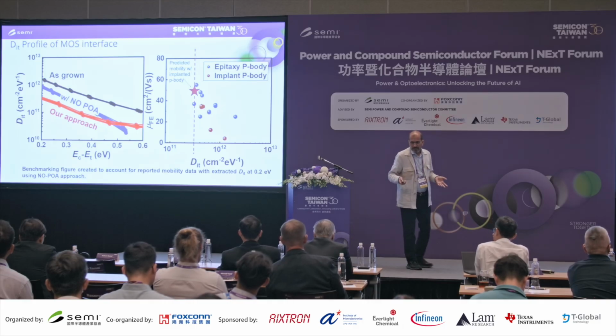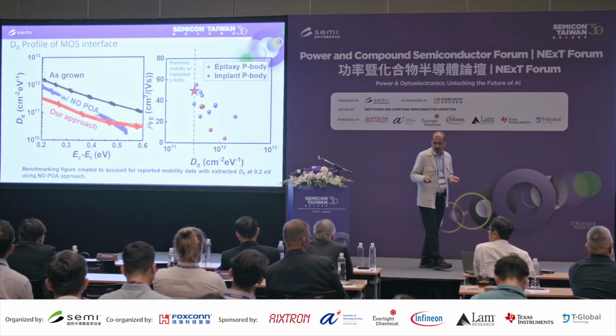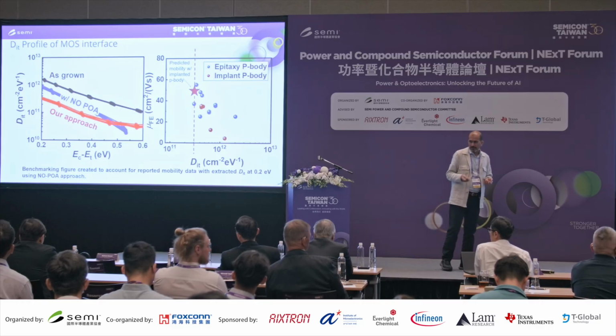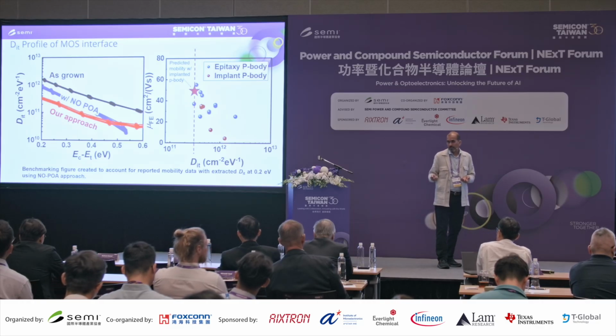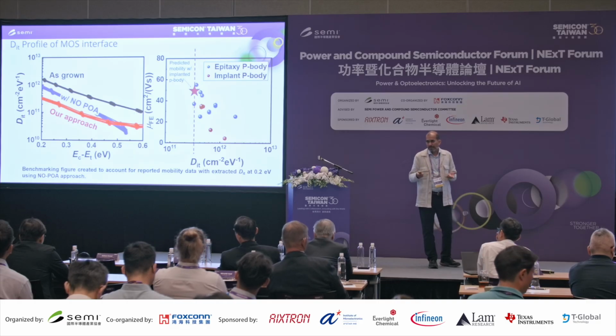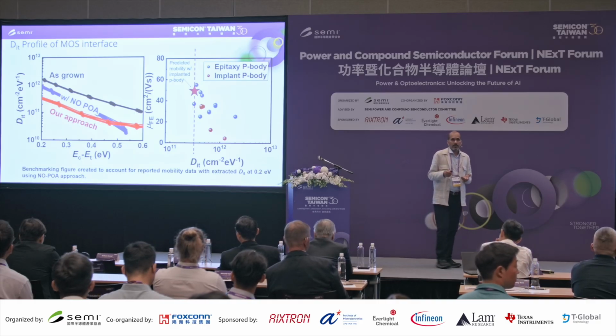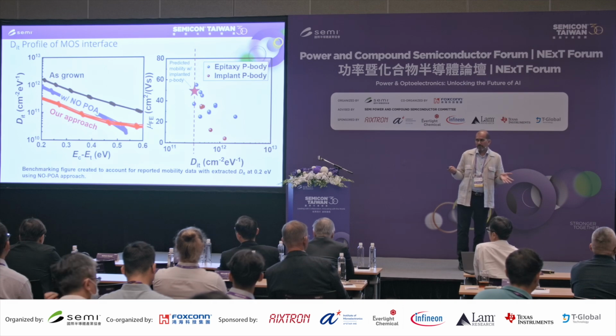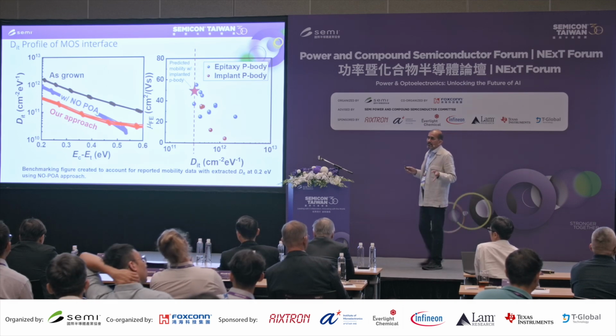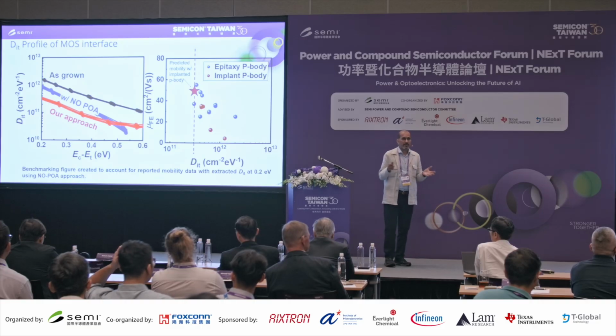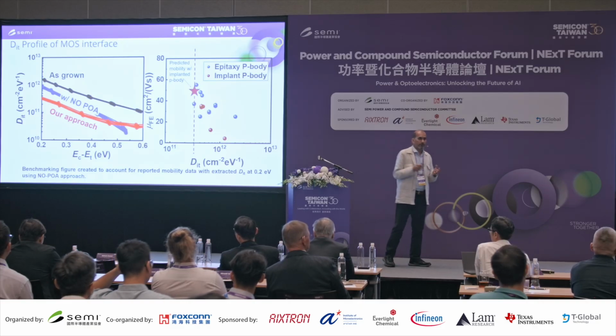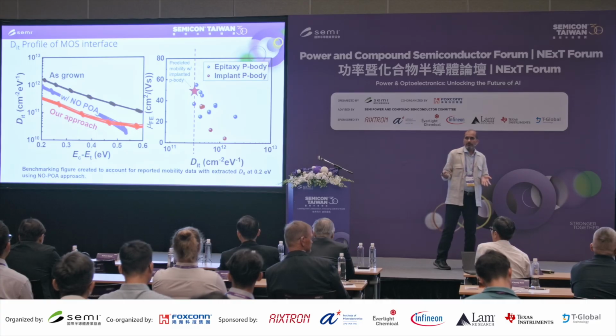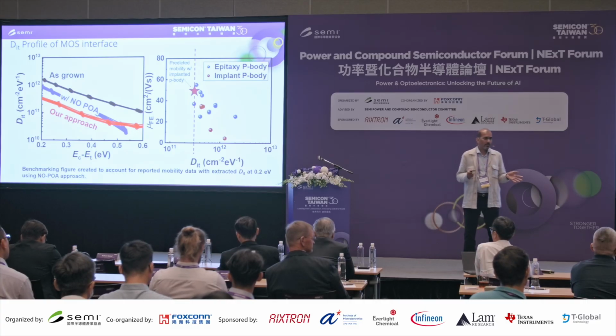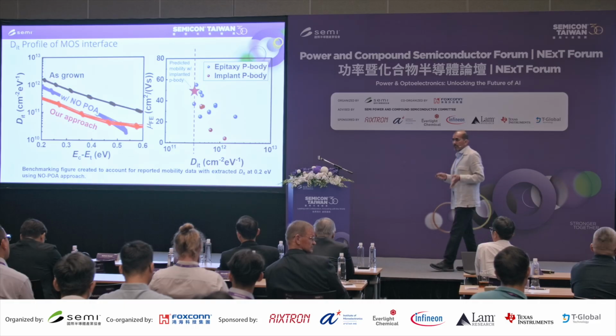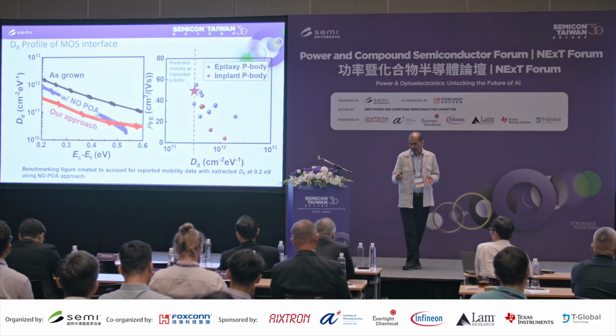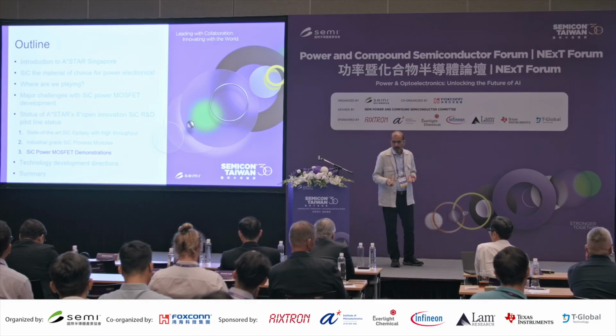This is just the DIT extraction, and you can see on the left side we have gotten a DIT of about 2E11 or 3E11, and the predicted mobility from here is about 55, which is at least 3 times better than what people report on product devices. The process we are using here is very different from what you may find in some research papers, where people just use ways to improve that are not manufacturable. When we develop the technology, we are very much focusing on manufacturability and simplicity so that cost is low, and we are going to get good mobility with simplicity and low cost.